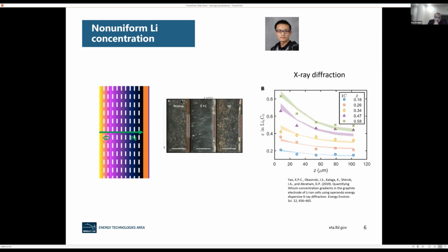So the pristine graphite looks completely black. 0.1C charging, as you can see, changes the color, but it's almost uniform color. This is just a current collector. 1C means I charge it 10 times faster. You can see this is much more gold-like here and much more black here. That means there's a concentration gradient, right? And people have observed this concentration gradient using X-ray diffraction, right? This is a paper which shows x in Li_xC6 as a function of Z, the Z direction, and depending on the state of charge, there is a significant concentration gradient, right?